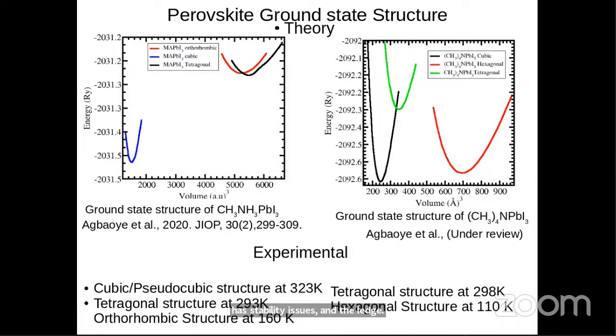But in tetramethyl ammonium lead iodide, I think previous work has shown that the stability issue is minimized, although we still have lead which could be toxic, but we have a more stable material in this case. So we want to see what we can get from this material and see if it could be better or have the same experimental efficiency as that of methyl ammonium lead iodide. Similarly, tetramethyl ammonium lead iodide also has different structures. It has the cubic structure, the hexagonal structure, and the tetragonal structure. The cubic structure at high temperature, the tetragonal structure at 298 Kelvin, and the hexagonal structure at low temperature.